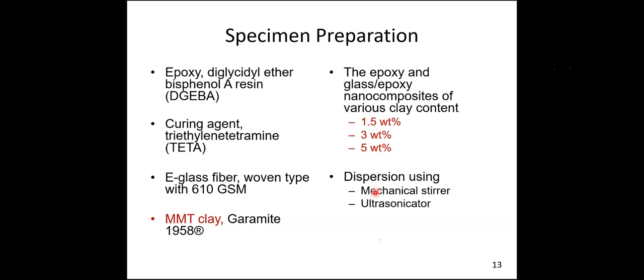And how to disperse it? Now I have taken different clay percentages and I have taken epoxy. We use a typical mechanical stirrer for mixing the clay with epoxy. Again, to have a better dispersion, we use an ultrasonicator. So this is the procedure to prepare the epoxy clay nanocomposites.